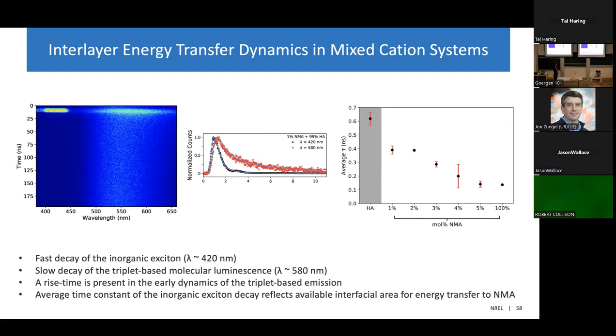So in order to actually analyze what's going on at short timescales, I'm going to subtract that as a constant background, and the resulting curve is shown in red. So there's some interesting things to note here. First of all, like I said, there's a fast decay of the inorganic exciton, which is consistent with the energy transfer into the organic layer. And then there's also a subtle rise time present in the molecular emission, which you might be able to see slightly in this red curve. That again is indicative of the energy transfer process.